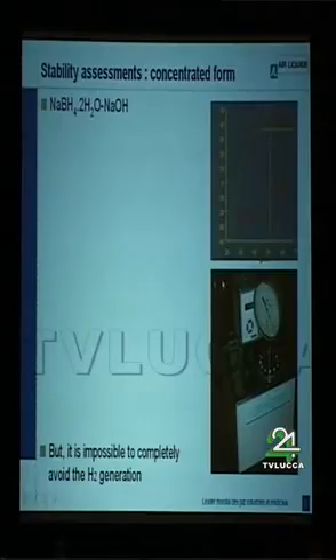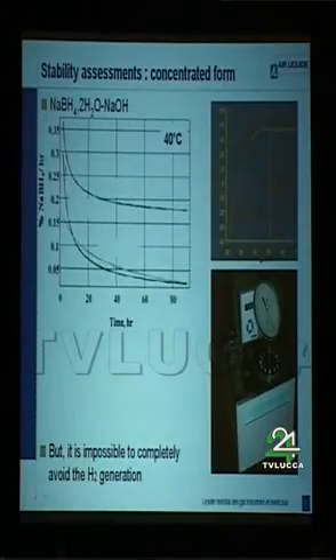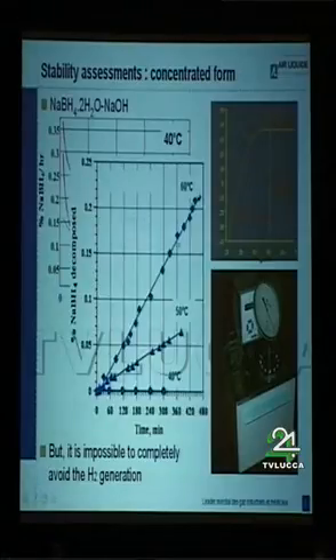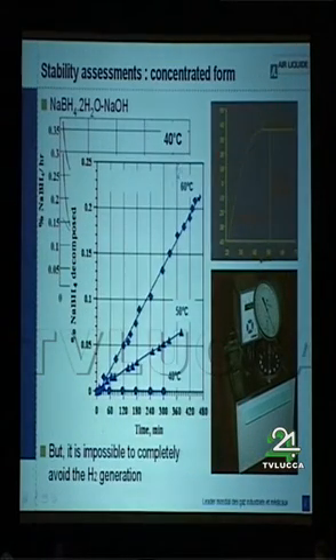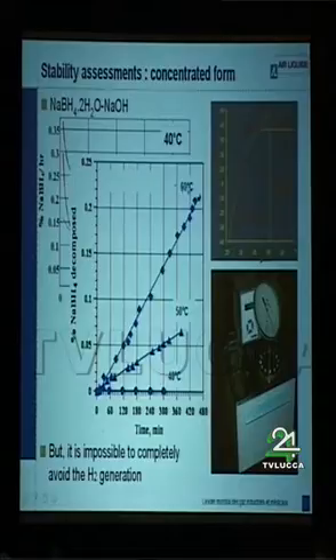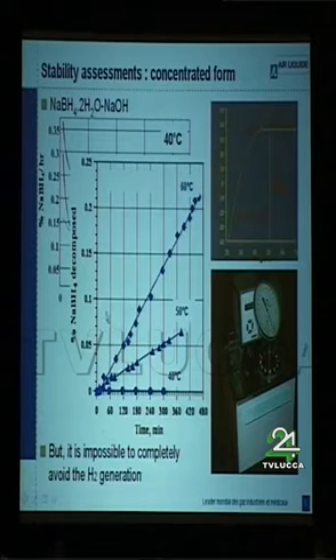So we also performed some assessment for the concentrated form of sodium borohydride in order to know if this formulation is stable with time, with a very low concentration of sodium hydroxide. So we made many experiments, and we varied the sodium borohydride concentration and NaOH concentration at 40 degrees, and you can see here that the release is improved, but it's still existing. If we make the temperature vary, as it can be in reality, of course, the decomposition increases with temperature. So it is impossible today to completely avoid the hydrogen auto-generation in the storage.